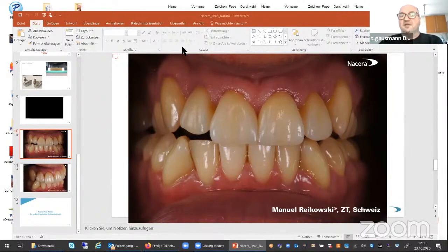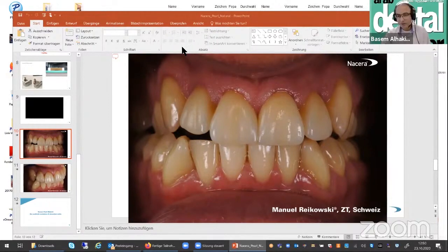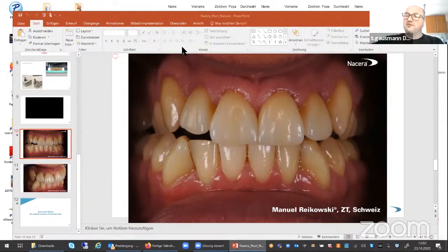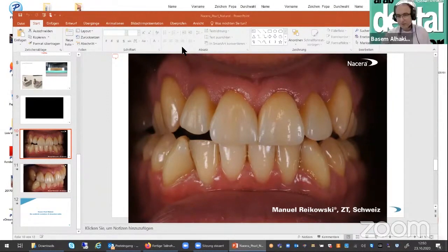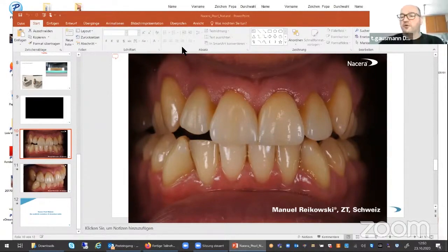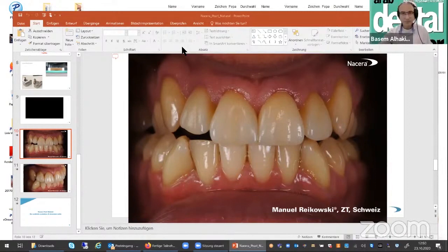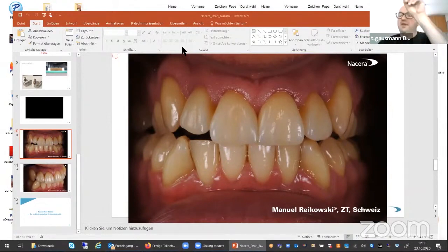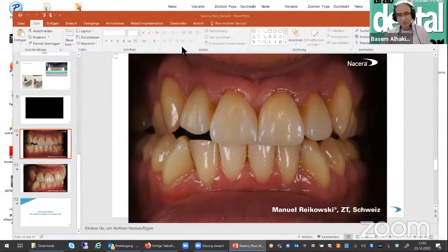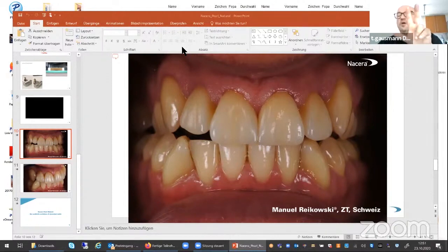This is depending on the situation. The only thing I can tell you is that the connection, when you've got a large span bridge, should be where you have the canines, where it goes into the curve, and on the last units. So when you've got, for example, a bridge from 7 to 7, here at least in Europe we say 7 to 7, you have to connect at 7 and at 3 and maybe at 1 interdental. So this is 3 connectors to the sinter support.